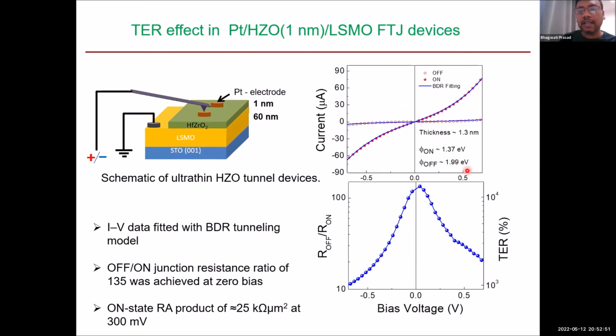Then you can see the IV, where we cycle the voltage between plus minus 0.6 volts, which is basically to make sure that you are not switching back the ferroelectric material when you apply the read voltage. So you see this is the off state current, and this is the on state current, and we fit them with the BDR model, and from that we got the barrier height. There's a large difference in the barrier heights for the 2 different directions of ferroelectric polarization. So we have seen a large on to off ratio.